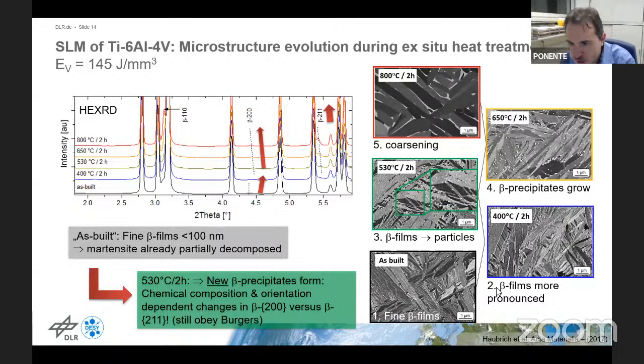And on the right-hand side, you see some SEM images corresponding to samples treated in that way. At the bottom, it's difficult to discern, but there are these fine white films in between the martensite lath. And going to higher temperatures, the films get more pronounced at 400 degrees, but they completely break up at 530. Here we only get very fine white particles in the SEM images of the materials. And these particles coarsen at higher temperatures, which you can see here in the yellow and red framed images. So there's a lot happening in the material.